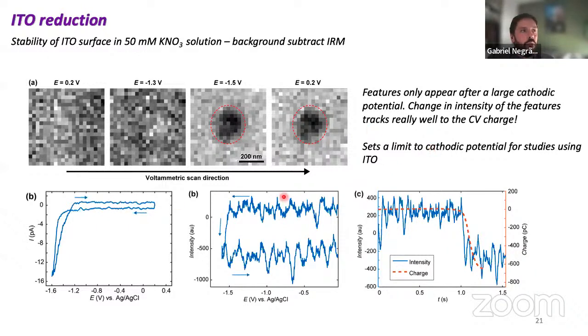We do some background experiments where we record CVs, and the electrolyte is just potassium nitrate. We can see a very flat CV until we get here, which is just electrolyte discharge, so just oxygen reduction and hydrogen evolution reaction. If you were paying attention during the whole school, you will notice that something is happening here, right? Remember, potential is the energy I'm giving, and current is the speed of the reaction. On my forward sweep, I have to give a lot of energy for the reaction to happen, and then it happens with a given speed. But in my reverse sweep, I need to give less energy for the reaction to still be happening quite fast. So this crossing point is just a telltale sign that something happened on my surface and it was modified, right?